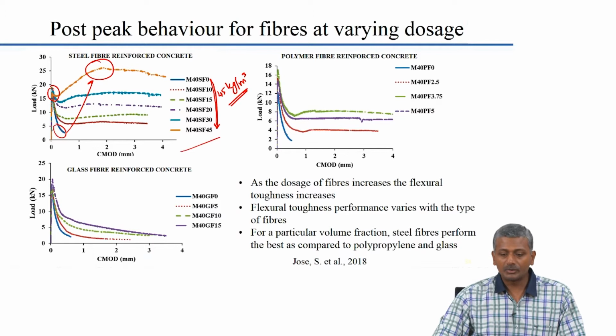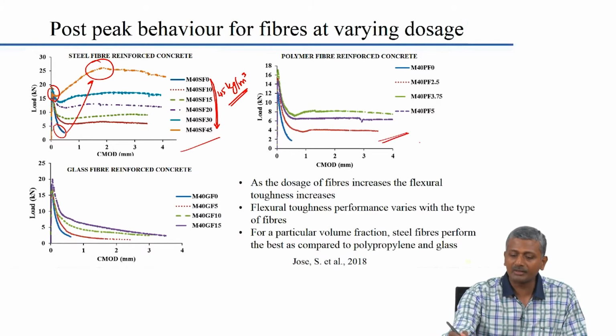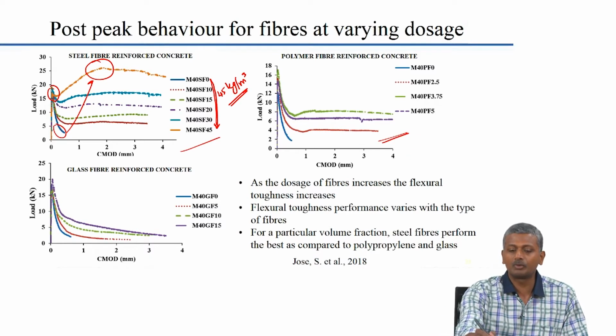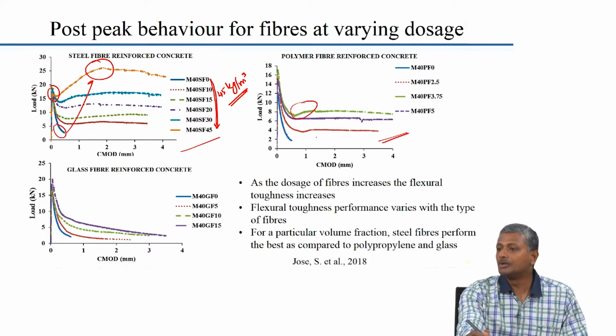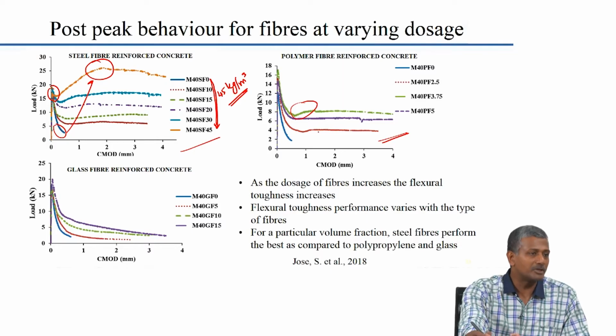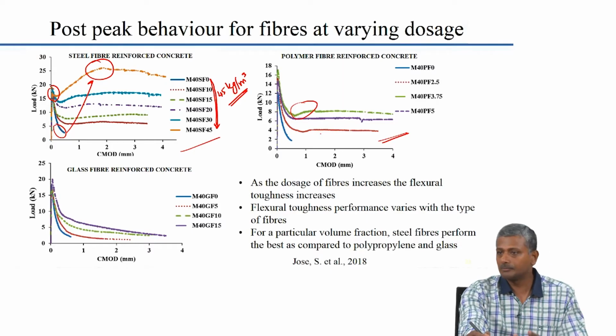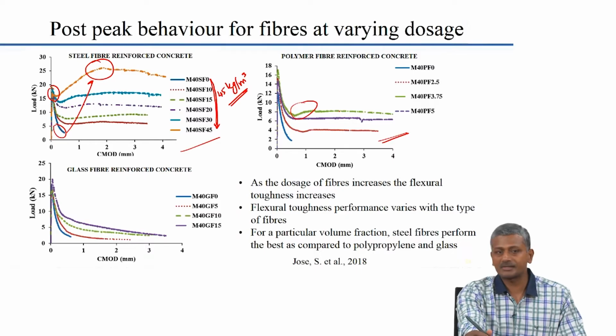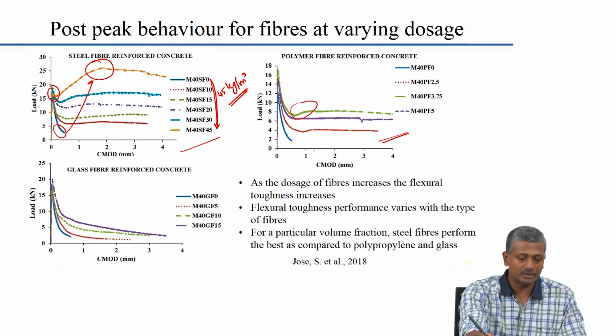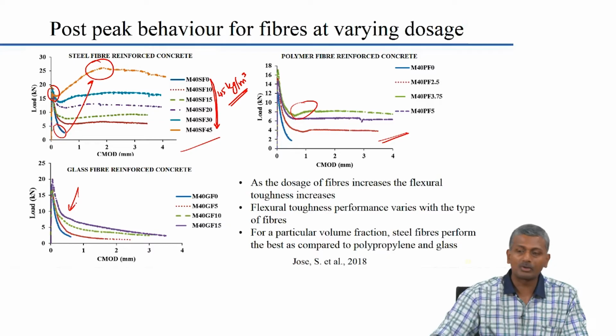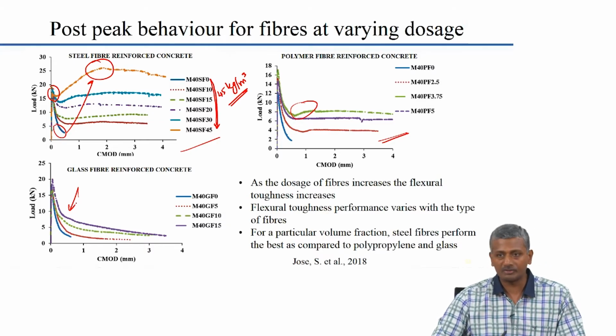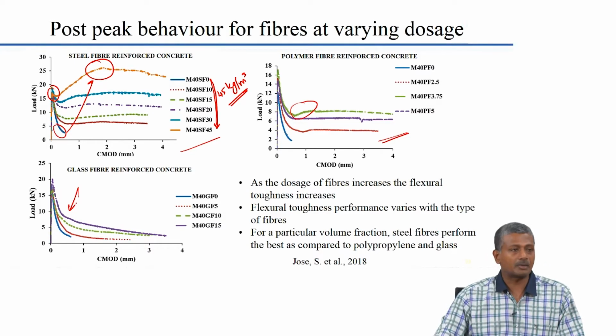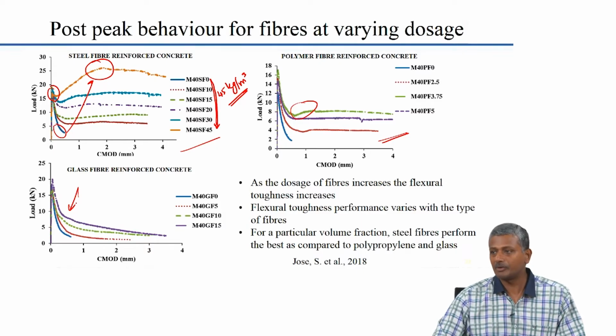Okay. So, in terms of polymer fiber reinforced concrete, there is only a certain maximum to which you can actually go. You do not really get too much additional contribution from the polymer fibers, because the extent of stress that can be carried by these fibers is very small, right. Polymer fibers are not that strong as far as tensile loading is concerned, steel fibers are much stronger than that. Glass fiber, the problem is more related to the brittleness. You really do not get much deformation, and the fiber may start rupturing before you get sufficient pull out from the matrix. Because of that, the performance of glass fibers is not really as good as that of steel fibers.